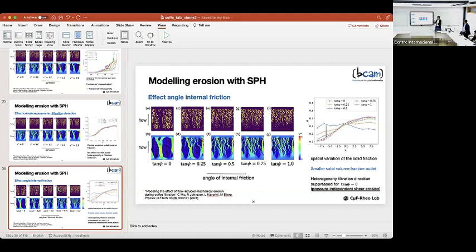Yeah, there are two things. One thing that I discussed at the beginning is one model to reproduce the time-dependent effects. Time-dependent effects are due to fine migration, and then eventually we are saying, okay, good. When they migrate, they do not offer any resistance because they are in a kind of free flow. And when they are stacked, they will produce a resistance which is increased.